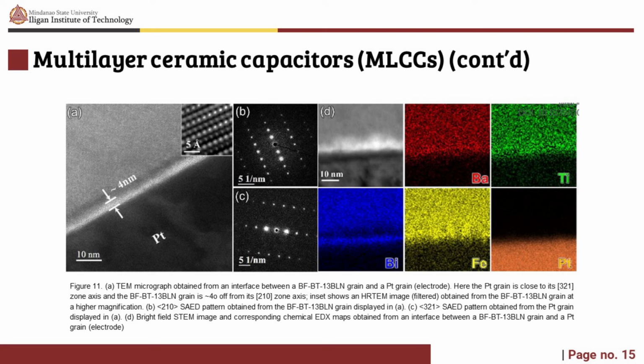According to the EDS elemental maps presented in Figure 11d, the amorphous layer is rich in barium, titanium and iron, but deficient in bismuth. Bismuth, however, is present at the surface of the platinum. These similar amorphous layers have been reported in BT-based MLCCs, and their formation can be attributed to binder burnout during the sintering process.